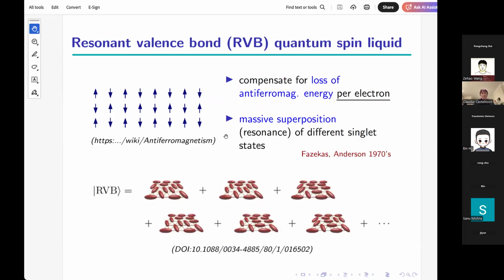And so the idea that Anderson and Fazekas had to compensate for this loss is to think of lattices where, instead of a perfect antiferromagnetic arrangement like a square lattice, you cannot have it, like the triangular case. And then you think about a possible state that is a superposition of all possible ways of pairing up the lattice into nearest neighbor pairs that form singlets. In this case, you have an exponentially many states, and it gives you an even more enhanced gain in kinetic energy between them.